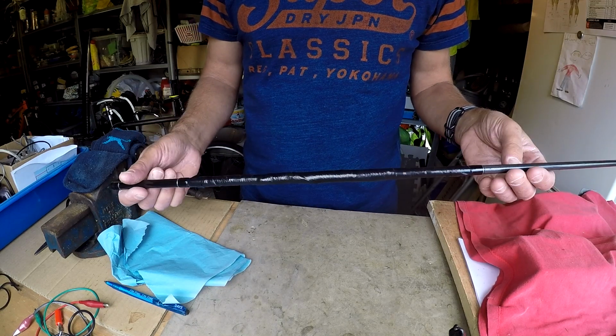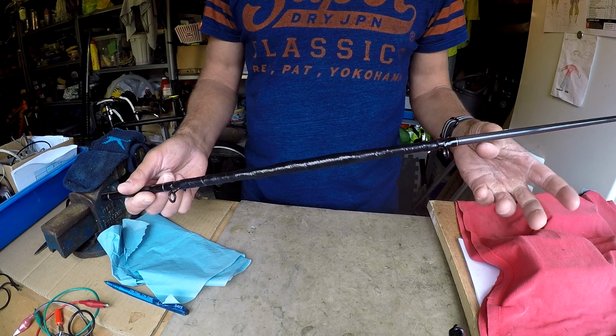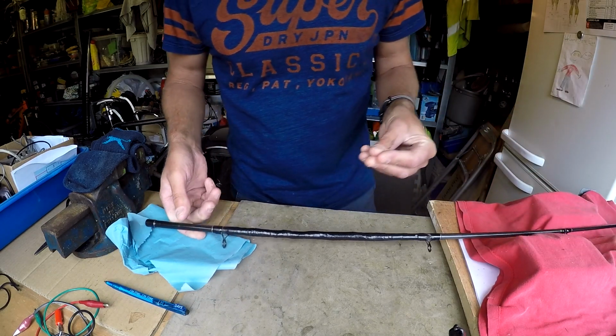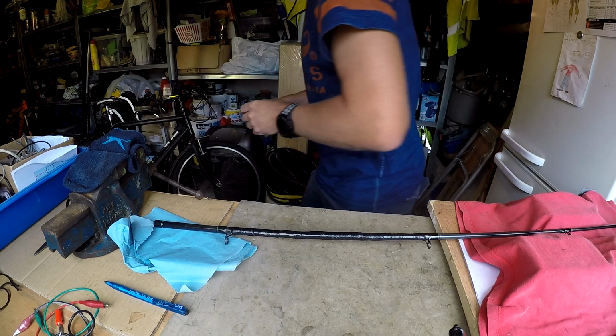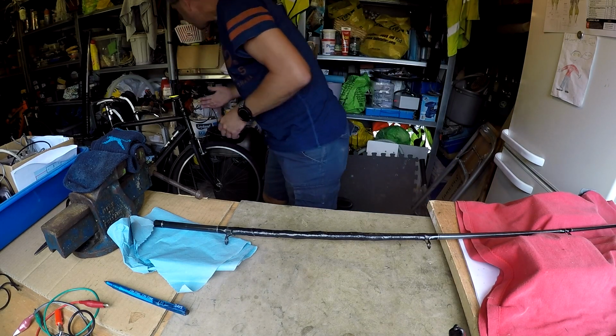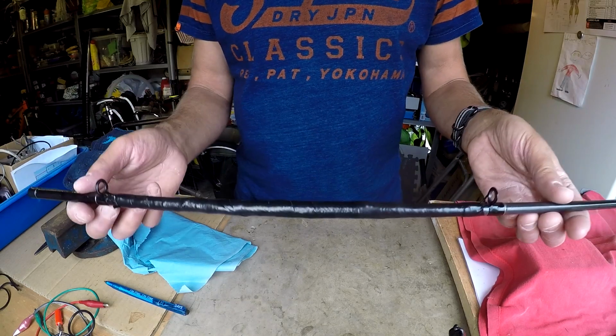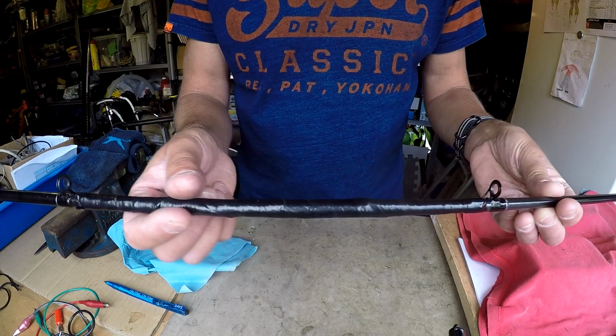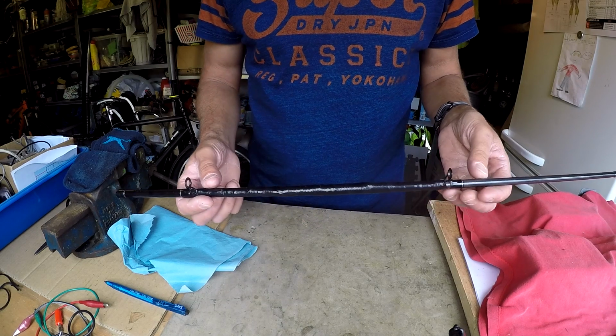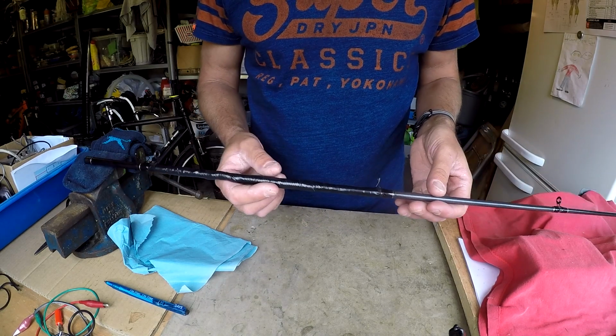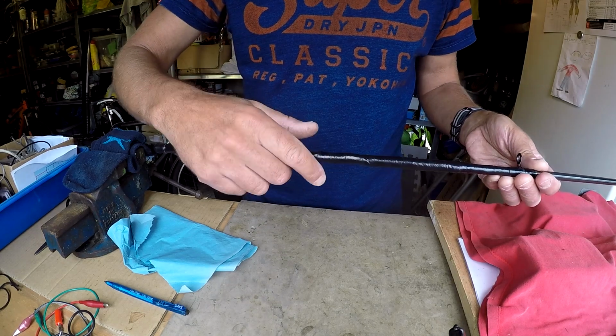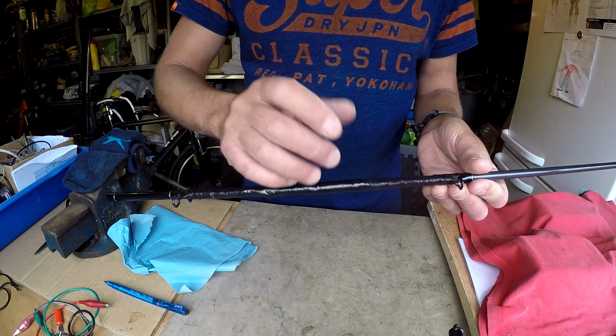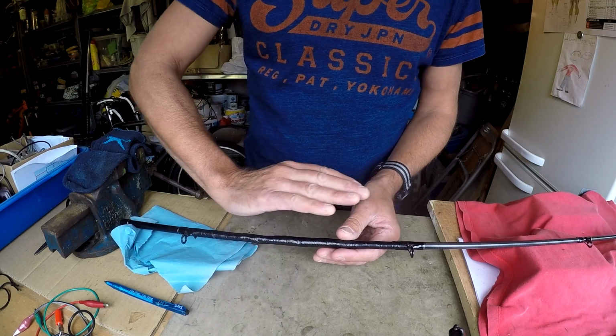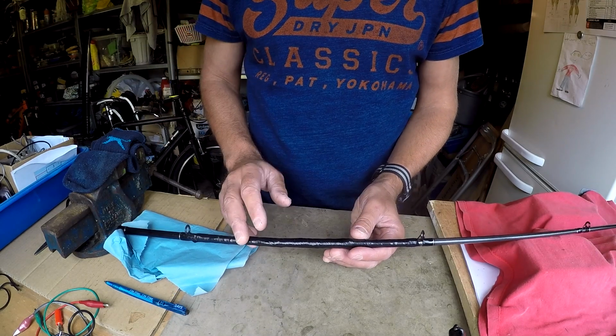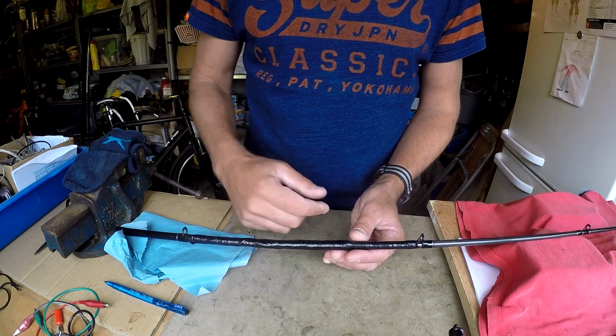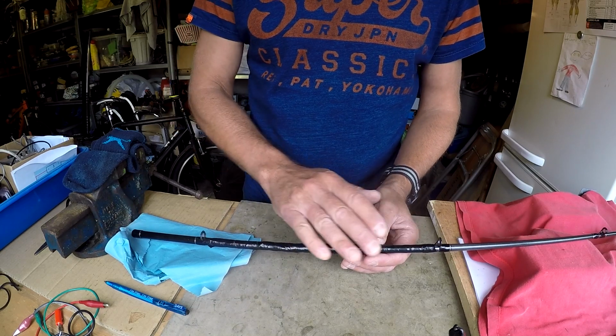right, it's been about 18 hours now. Last night I managed to get the carbon fibre round and put some more epoxy on there. What I found was, it's not too bad. What I found was the carbon fibre sheet, because it's a small circumference, was quite thick and rigid, and it wouldn't mould around. I think you need a thinner sheet for something with a smaller circumference. The sheet needs to be a lot thinner so it takes to the tackiness.